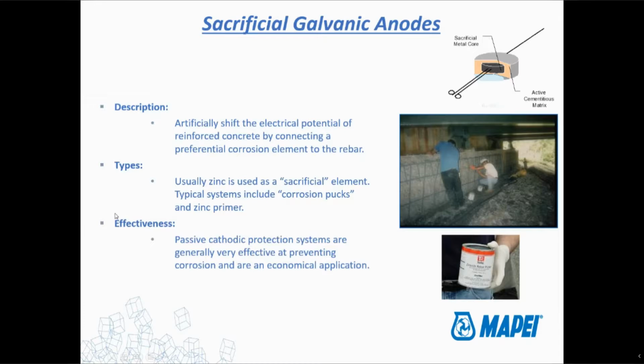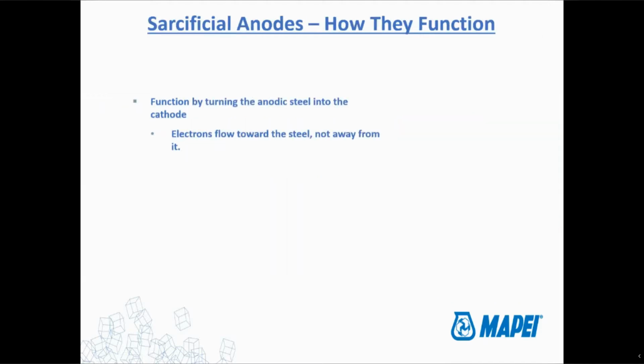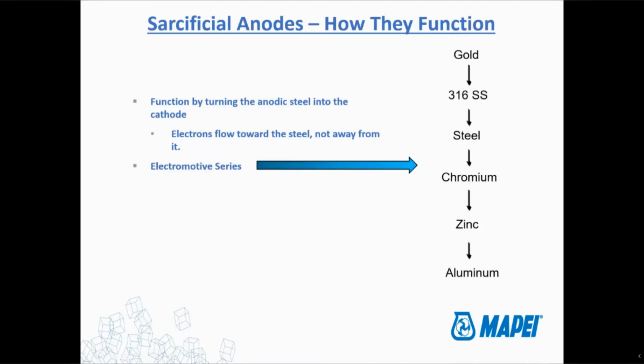Really, any kind of concrete patch that you're doing, it's a really good idea to use zinc anodes. There's also different forms. There's zinc-rich coatings that you can use as well, and even just rebar coatings that prevent the steel in the patch area from acting as the cathode in the reaction work as well. So you really should always be doing something along those lines in a patch. How they work is they basically turn that anodic reinforcement steel into the cathode. That forces the electrons to flow toward the steel and not away from it. If you remember, the corrosion happens where the electrons are leaving, not where they're going to. So we want the electrons to be going to the reinforcement steel, not being pulled away from it.